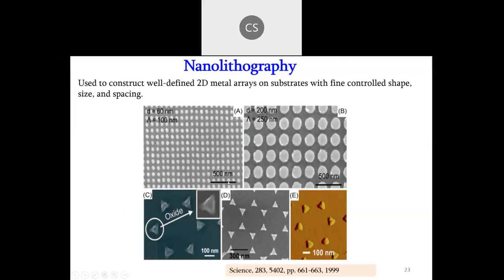You can see this is a 500 nanometer scale. Almost all of the small gold nanoparticle dots are less than 50 nanometers. The most interesting point of this nanolithography, you can see here from the top to the bottom, is that if you want to make hundreds or maybe 1,000 nanoparticles on a single platform, for example in a sensor, a gold nanoparticle of maybe 100 nanometer size, 100 numbers, we can do it with the help of nanolithography, and each nanoparticle can help to enhance the sensitivity as well as the selectivity of the sensors. So this is the main advantage of nanolithography-based material development.